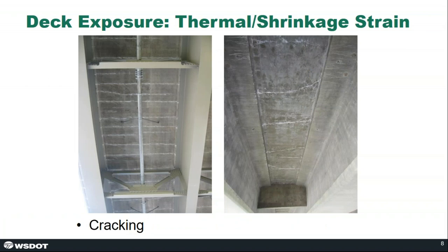And we also have thermal and shrinkage strains of the bridge deck. These strains often lead to cracking within the decks themselves, as the decks are often composite with the girders and elements that support them. This sort of cracking has been fairly common throughout the country. It's something that a lot of states are working to solve, and there have been a number of improvements in minimizing this sort of cracking in recent years. And the cracking is obviously undesirable because it allows moisture to penetrate deeper into the deck, and it can accelerate the other types of exposure and deterioration that we're concerned about just on the deck surface.